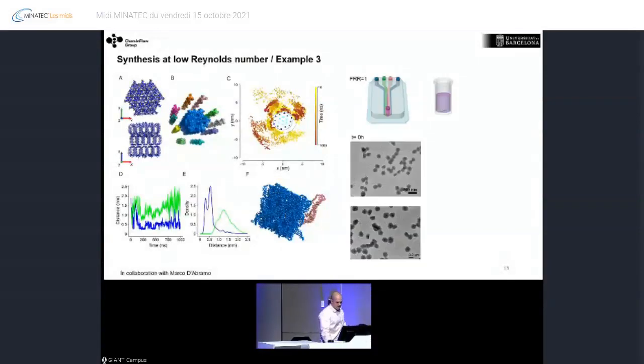And what you see, if you look at the density and distance, is that in fact the growth is initially favored from the vertices. So this clearly confirms the experimental data that we obtained, okay? Another important fact here is that with microfluidics, we can isolate the nucleation species, because we can collect whatever is generated in a few milliseconds on a TEM grid after the synthesis in the microfluidic device.